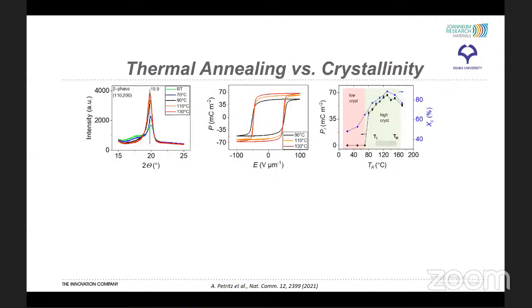We have also performed a very careful investigation of the influence of thermal annealing of the ferroelectric layer. In Xrd measurements, we have observed an increase of the crystallinity for annealing temperatures in the range 70 to 130 degrees. 130 degrees is above the Curie temperature of 105 degrees, but below the melting point. The crystallinity in Xrd was parameterized roughly by the height of the 110 reflection peak. The increase in crystallinity comes with a proportional increase in the remanent polarization and also a decrease in the coercive field, and that can be seen clearly in the hysteresis loops.